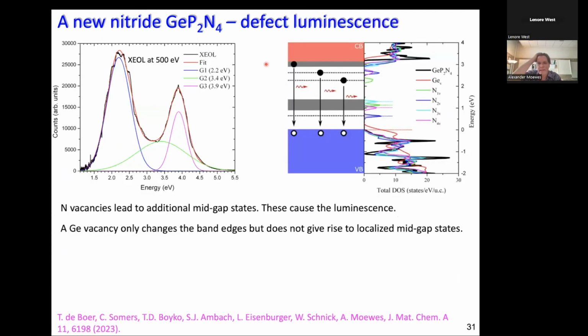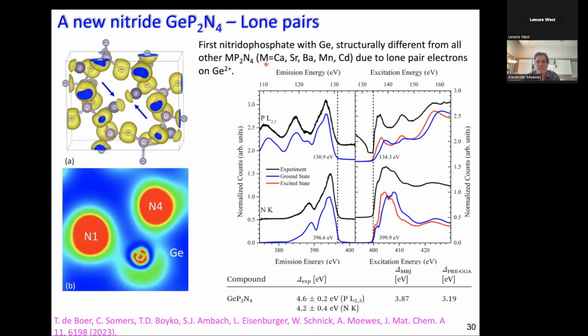But it didn't stop quite there, because we were surprised. Remember, I just showed you the band gap. We won't dwell too much time here on exactly what the energy is, but the bottom line is a wide band gap semiconductor is what I would refer to. Maybe some people would even call it an insulator, depending on the two edges, what the band gap is. So clearly there should be no visible luminescence, because the band gap is just too large. When you have an electron crossing 4.2 to 4.6 electron volts, this would be in the ultraviolet.